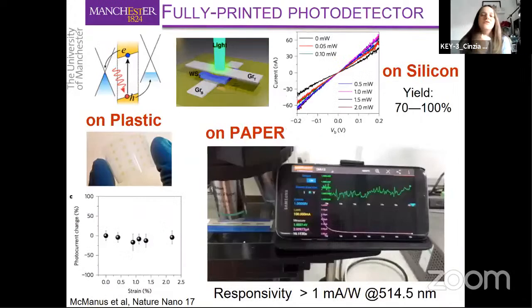Okay, so then with those inks, we started to fabricate a fully printed heterostructure, and the first device that we made was a photodetector, and this is a 3-layer heterostructure. We have 2 graphene electrodes, one at the top and one at the bottom, and in the middle we have the printed photoactive film, which was made of tungsten disulfide ink. And initially we printed on silicon.